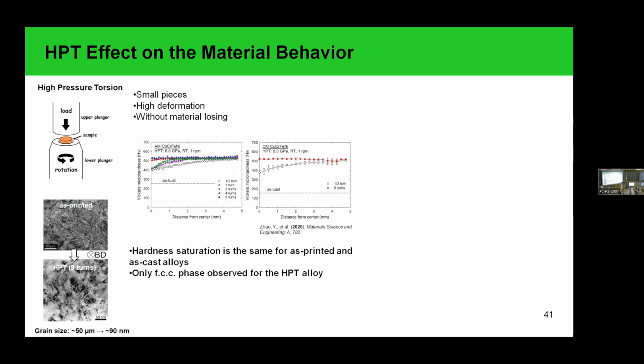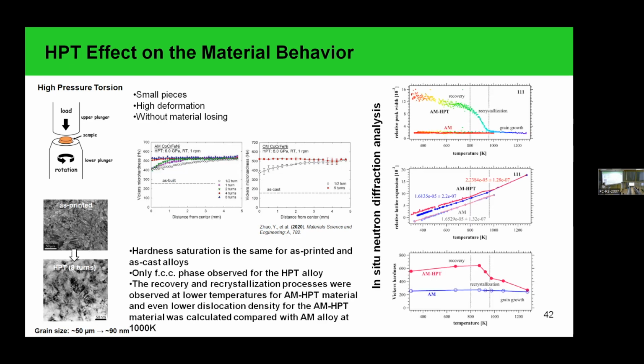We observed that it was the same as for the as-cast materials, approximately with the same number of turns or strain deformation level. Here are 4 turns of our materials, and here are 5 for the as-cast materials. Also for our materials, we observed the face-centered cubic structure only, even after 8 turns. Additionally, we observed interesting properties for these materials with the in situ neutron diffraction analysis.